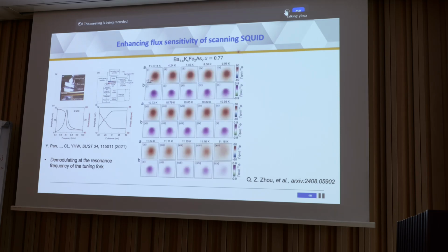So to test that it indeed works, we measured an integer conventional vortex in BKFA. The top rows are the so-called DC flux, which is the straight flux signal from the SQUID, and they look circular and nice. And the second rows are from this so-called demodulated AC flux signal. As you can see, they are slightly distorted from the circular shape of a conventional vortex because the demodulation is, in principle, measuring the gradient of the magnetic field rather than the direct magnetic field. But you can also see that the contrast has been enhanced in these AC flux images, so that we can make sure that we are indeed measuring the vortices.